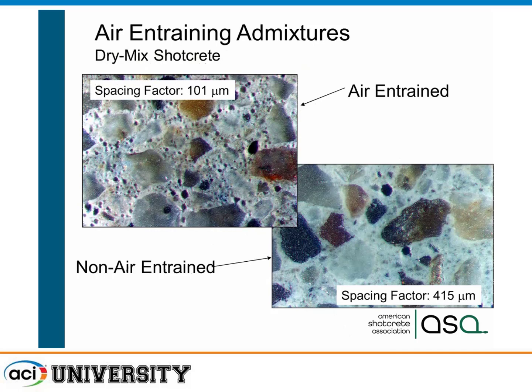And a lot of people say, well, what's up with the air content, with air entrainment? We use air entrainment in wet mix. You get it in the pre-mixed concrete truck. In dry mix, we actually have admixtures that are in the pre-bagged materials that will allow us to form these little air bubbles that are essential to having freeze-thaw durability. One thing that we do get, though, remember the impact? We're talking 60, 80 miles an hour.